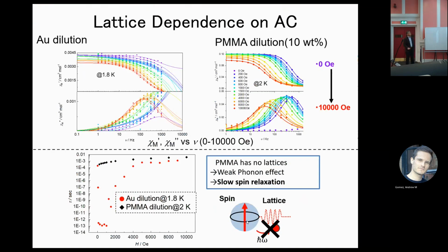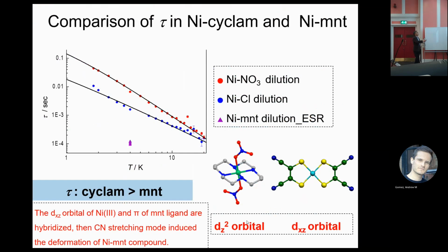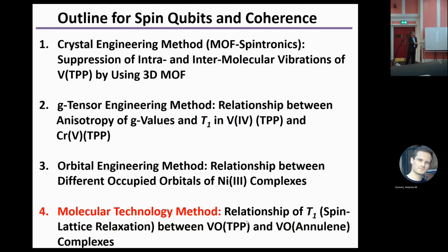So this shows a slow magnetic relaxation. So these are all the data. This is a nickel MNT. So nickel MNT has a strong lattice and molecular deformation, then the shortest lifetime. And nickel NO3 is the longest, and nickel chloride second. So from these results, Ni(III) is also a good candidate for the molecular spin qubit, but the nickel NO3 is best. So finally, the molecular technology method usually uses molecular design. Molecular design means that you think about some physical property by molecular design.